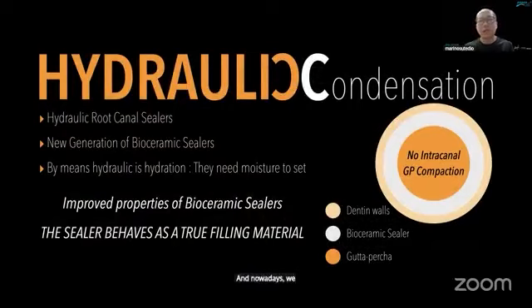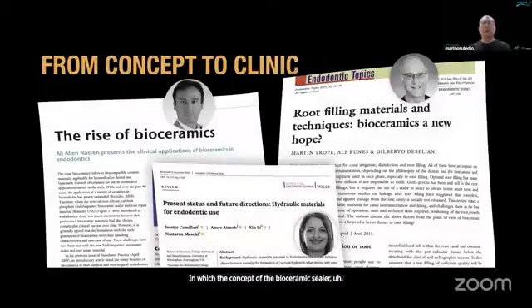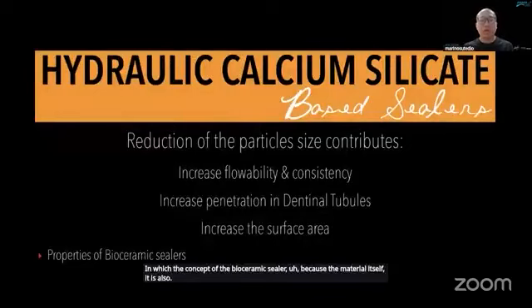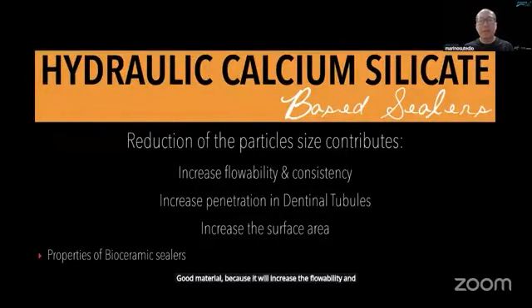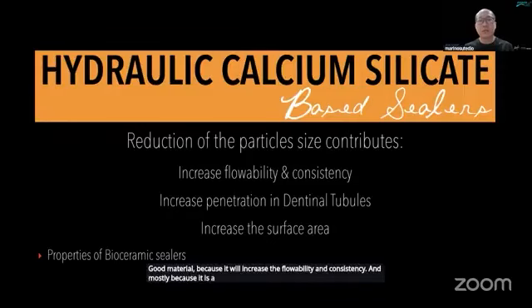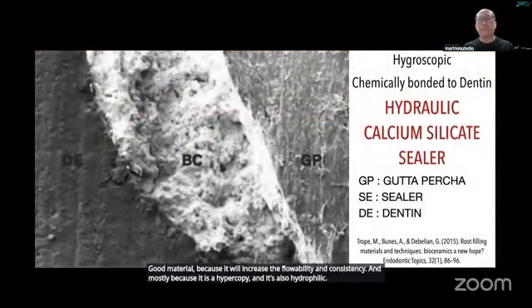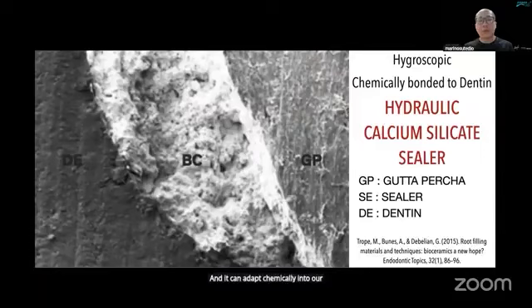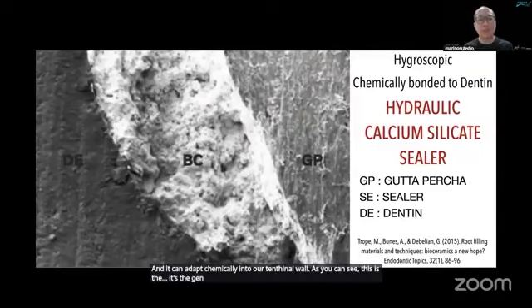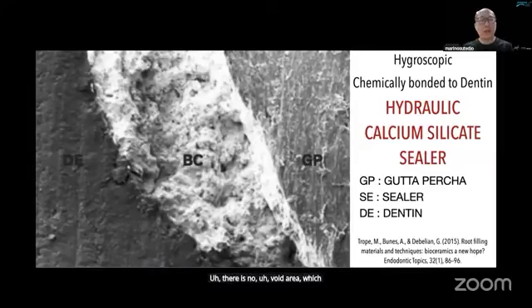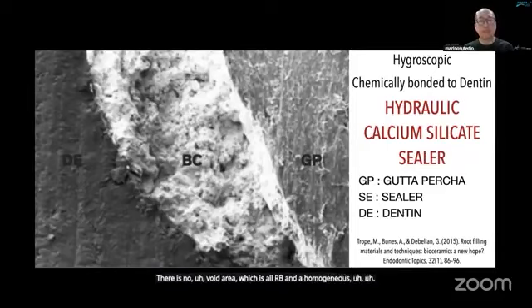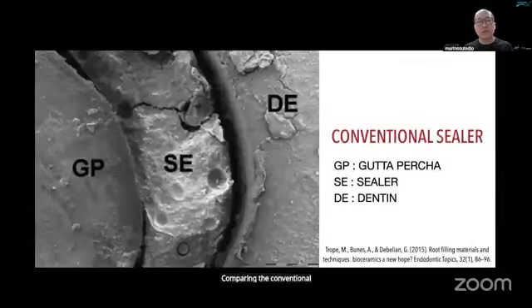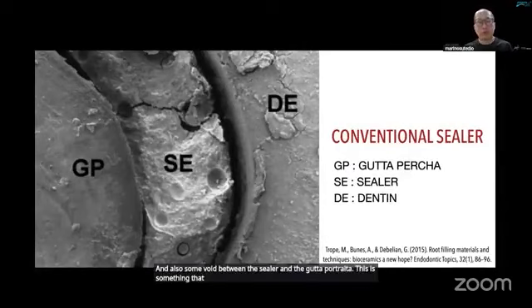And nowadays we are understanding the use of the bioceramic sealer, because the material itself is also a good material because it increases flowability and consistency, and mostly because it is hygroscopic and also hydrophilic, and it can adapt chemically to our dentinal wall. As you can see, this is the dentin, the bioceramic sealer is the BC, and this is the GP. There is no void area, and it is a homogeneous continuation. Compared to the conventional sealer, we can see there is a void between the sealer and the dentin, and also some void between the sealer and the GP. This is something that we do not want to have.